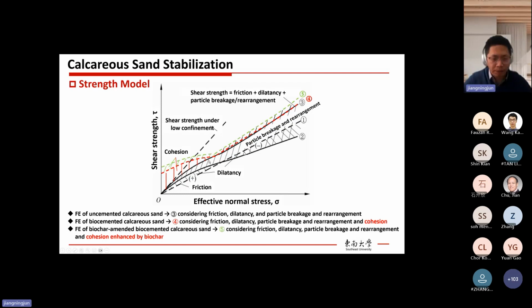Based on our direct shear and triaxial shear test results, we think that it helps most at lower effective normal stress or confining pressure range. At this range, we could see a dramatic increase in the cohesion. This is the contribution from MICP. However, when the normal stress or the confining pressure is high, the contribution from MICP is diminished. So it becomes aligned with the original failure envelope.